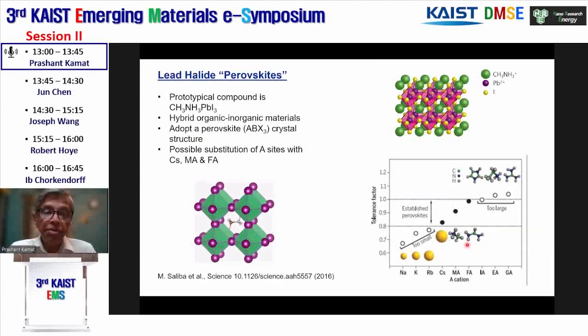But still, here is some information on lead halide perovskite. Again, most of you may know. I just want to give you an idea that these are ABX3 crystal structures. And then in the cavity, you can put either cesium, methylammonium, or formamidinium. And that sort of gives the perovskite structure. Only these three ions can be accommodated in this cavity. Others are too small or too large, but recent efforts have shown that you can dope these materials with other cations and get better structures and better performance.